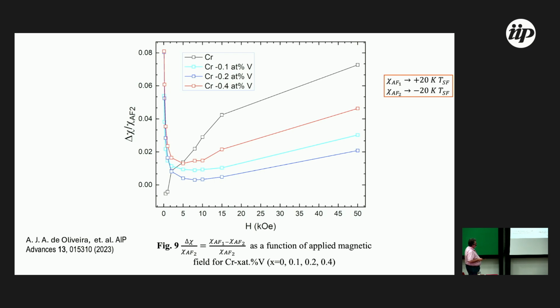Susceptibility AF1 phase: 20 Kelvin plus the spin flip temperature. Susceptibility AF2 phase: 20 Kelvin below the spin flip transition. Because spin flip transitions depend on the vanadium concentration, we put the same interval. Observe for chromium, the jump increases when the magnetic field increases. And for the other samples, 0.1, 0.2, 0.4, the jump is bigger when increasing the field and then decreases.